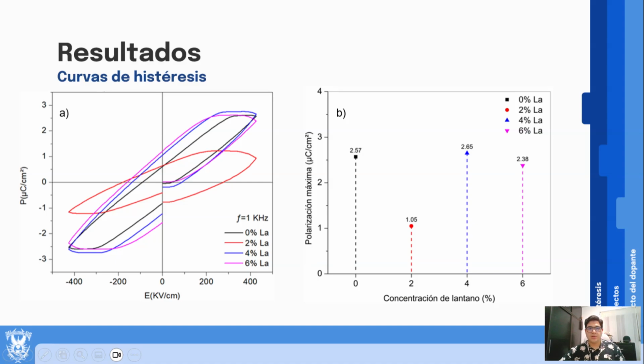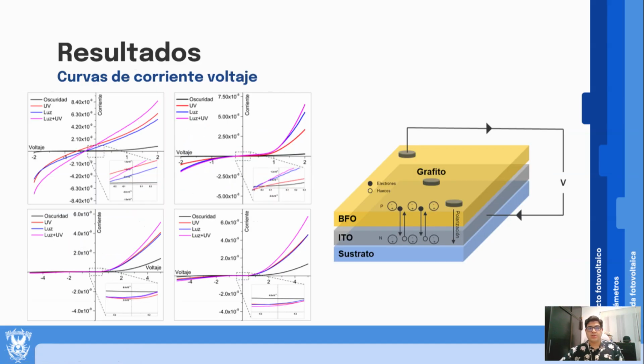The study revealed light-sensitive diode-like behavior in lanthanum-doped BFO films, with polarization states altering current-voltage responses. While zero-bias photocurrent confirmed photovoltaic potential, performance was limited by defect-driven leakage currents that disrupted stable polarization. These findings highlight both the promise for photodetectors and the need to minimize defects for solar cell applications.